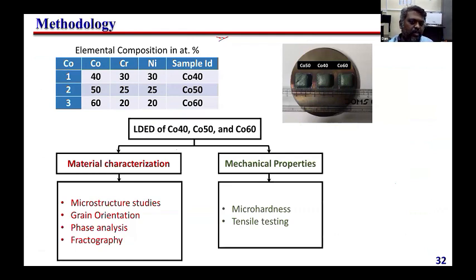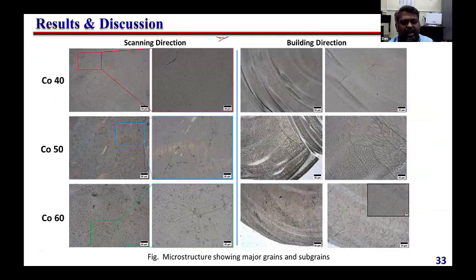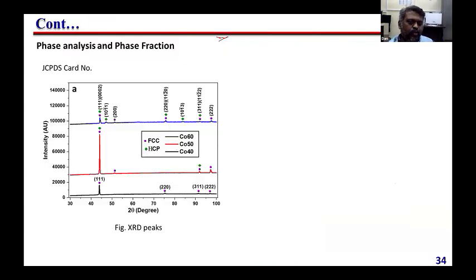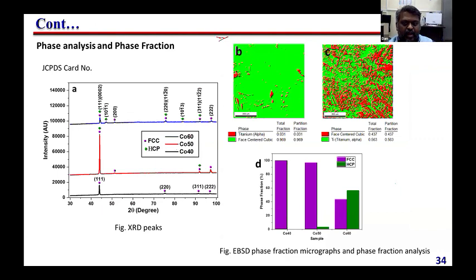up to 60%. Okay, in the case of equiatomic it is 33%, but we want to go for 40, 50, 60. So when you increase the cobalt content, clearly you can see there is a complete transition in the substructure. When you increase to 60%, the substructure is totally refined. We got it in a few micrometers. Also, when you increase the composition, other phases come in, like martensitic phases evolving at 50% and 60%. Up to 40% it is single phase FCC. When you go to 50 and 60, you can see a higher proportion of martensite, like here this red color is showing the other phase.